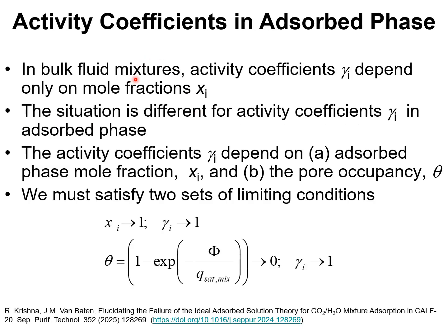In bulk fluid mixtures, the activity coefficients depend on the mixture compositions, say mole fractions x_i. The situation is different for activity coefficients in the adsorbed phase within microporous materials. In this case, the activity coefficients of any component i depend not only on the adsorbed phase mole fraction x_i, but also on the pore occupancy. We must satisfy two sets of limiting conditions.